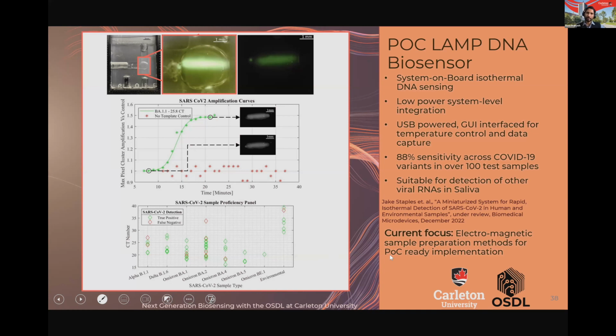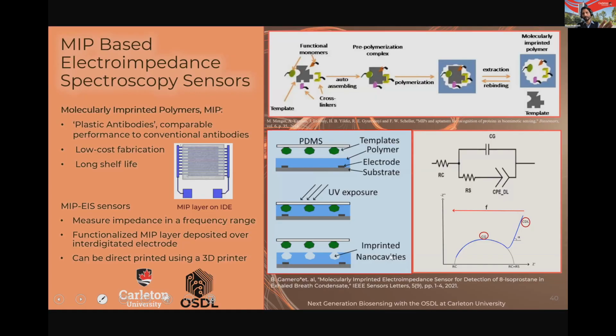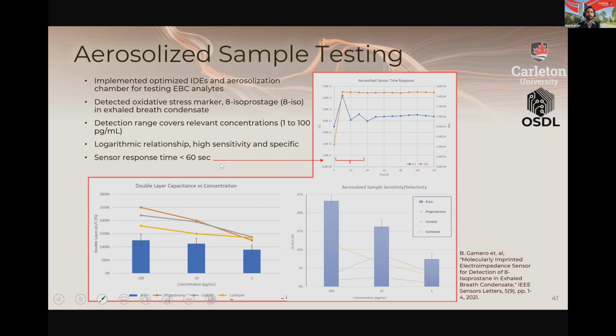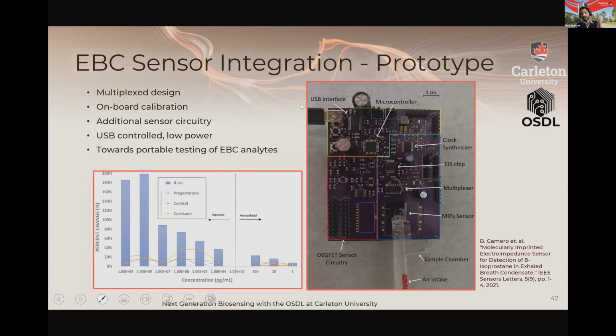And this is something that we submitted late last year, where we investigated its viability in a variety of saliva, nasopharyngeal swab samples, as well as some environmental samples provided to us by the Cube Research Cluster here in Ontario. And to show the viability, we have looked at other types of biorecognition molecules and implemented them for exhaled breath testing. So just a quick preview, using molecularly imprinted polymers, bound onto a simple microelectrode structure, we can detect a high impact COPD biomarker, oxidative stress biomarkers such as 8-isoprostane. And we have shown to interface this with an aerosolized channel to collect breath sample and essentially quantify presence of these markers.